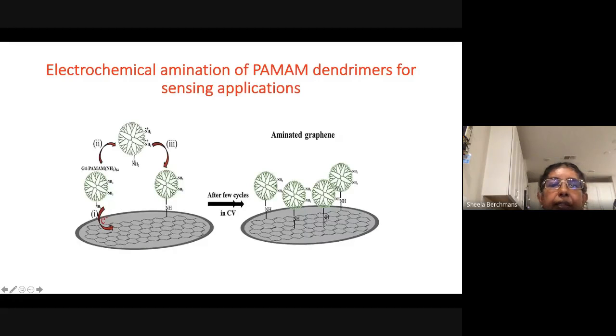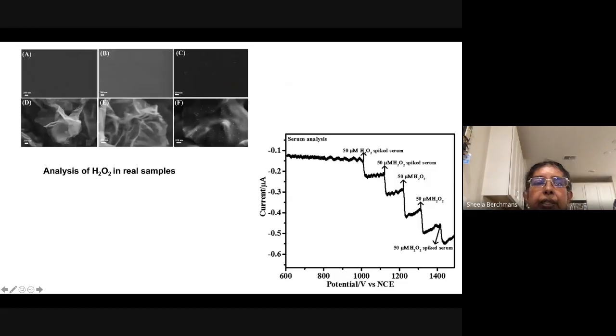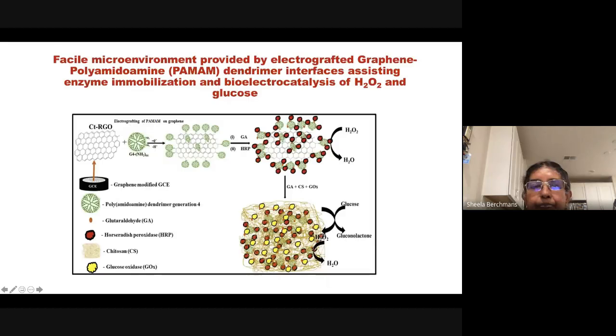In another work reported by us, we electrografted these dendrimer molecules on graphene surface. The dendrimer molecules can aminate the graphene surface. The graphene-modified GC electrode was electrografted with the dendrimer molecules, and these are the SEM images of the graphene-grafted dendrimer molecules. To this, peroxidase enzyme was initially grafted, and it was used for analysis of hydrogen peroxide in blood serum.